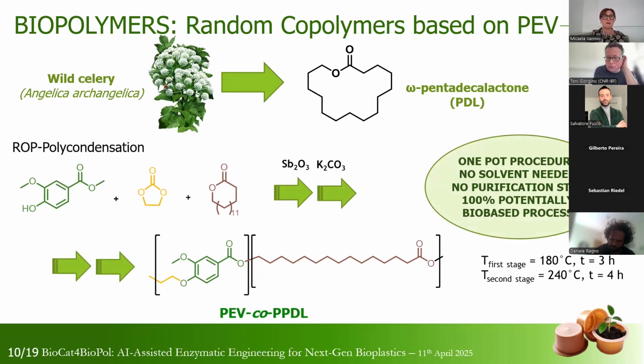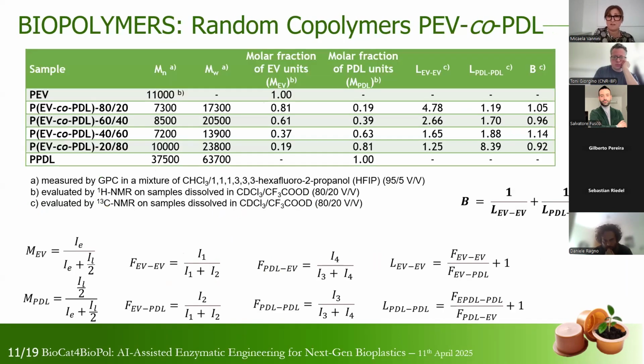So we prepared copolymers according to a protocol developed by our research group, consisting of a simultaneous derivatization of the less reactive phenolic OH with ethylene carbonate, and then a polymerization by both transesterification and ring opening polymerization. So the whole process is very easy, completely sustainable, because no solvents or purification steps are necessary.